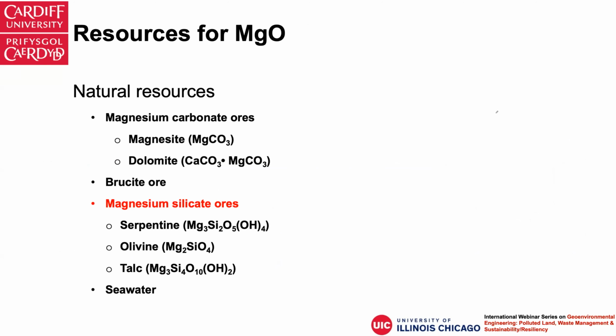If you look at the current resources for magnesium oxide or magnesia, the main natural resource we use to produce this material, commercially available magnesia, is magnesite. So it's a magnesium carbonate ore. That probably accounts for about 70% of the current commercial magnesia we can get. And we also have some magnesia from seawater precipitation and then calcination.